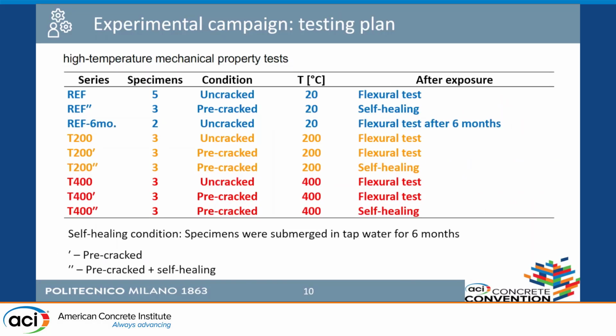So it's not an easy table, but summing up, what we did is we have specimens that have been heated without any pre-cracking. Then we have specimens that have been heated, but before heating, we pre-cracked the sample. And then there are samples that have been pre-cracked, heated, then we wait 6 months and we perform the test. So in this way, we see the effect of pre-cracking before the heating process, and the effect of the timing starting from the cooling of the specimen. So on the 3 sets of samples, the third one was meant to study the self-healing effect in the 6 months after the end of the thermal treatment.